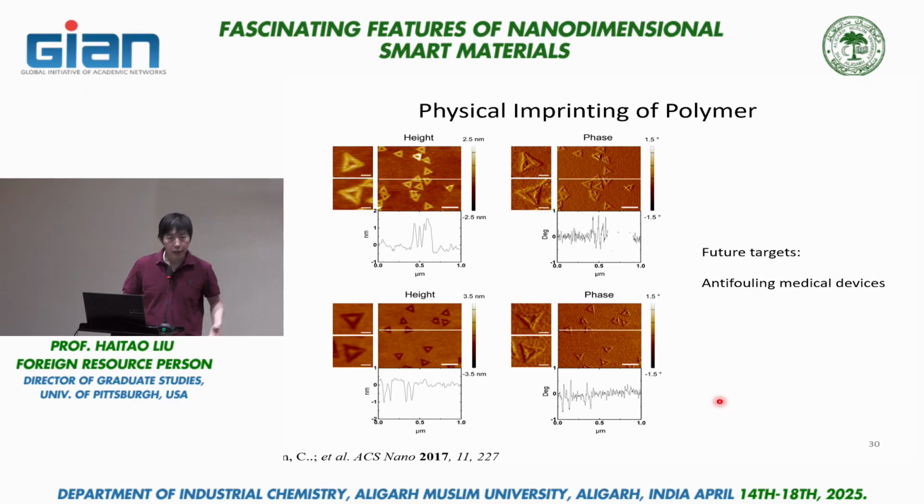All right, so I just mentioned that we're interested in patterning polymer, and with a DNA structure, we tried a different approach. Here we demonstrated that you can use DNA structure as a stamp, as a physical stamp, to imprint its shape by mechanical force onto polymer. So on the top, again, are those triangle structures that we used. And on the bottom are polymethyl methacrylate polymer surfaces.